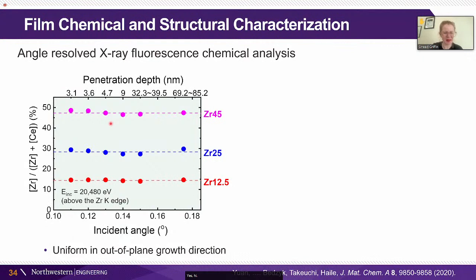Yes, hi. Thanks, Sossina. I was just wondering, since a lot of this is driven by this coordination, this competition between the 8-fold versus 7-fold coordination that the zirconium allows, would there be a way of controlling these effects with strain or substrate templating that will allow you to sterically control this? Yeah, that's a good idea. We haven't explored that. There are folks who've tried to use strain on films to change the catalytic activity, change the oxidation state, change the ionic conductivity. That's been a big effort.